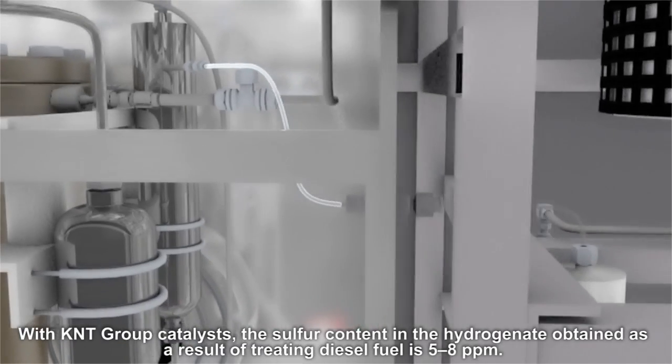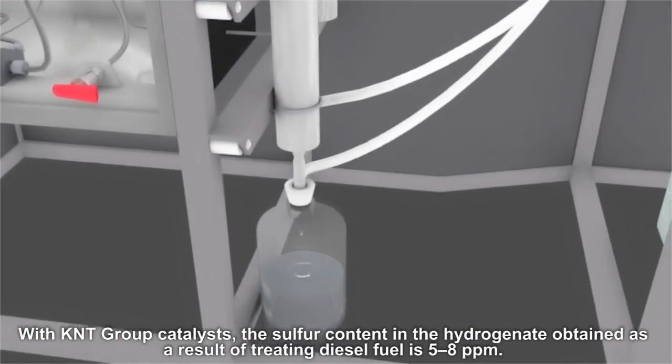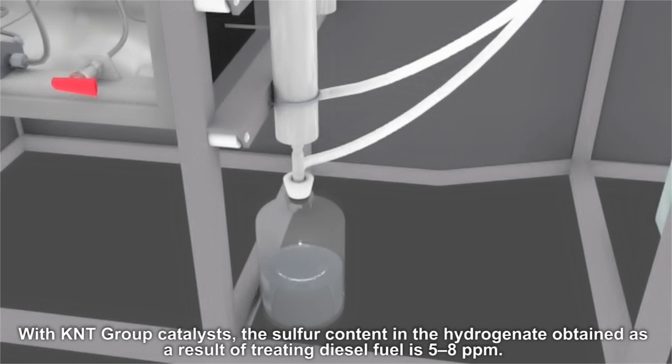With KNT Group catalysts, the sulfur content in the hydrogenate obtained as a result of treating diesel fuel is 5 to 8 parts per million.